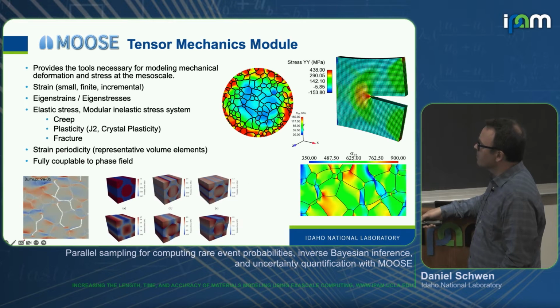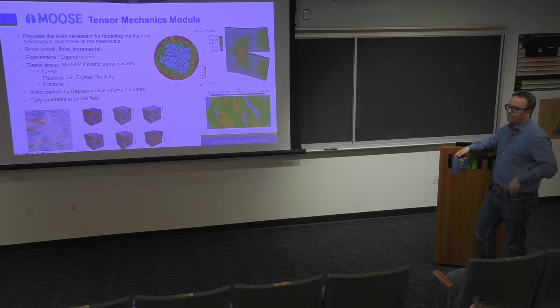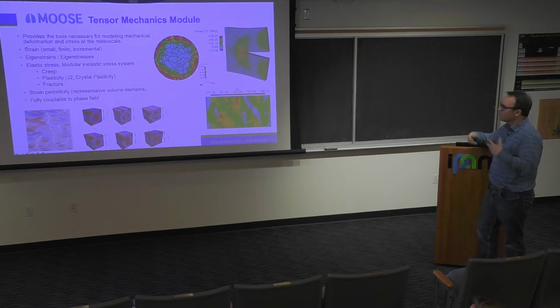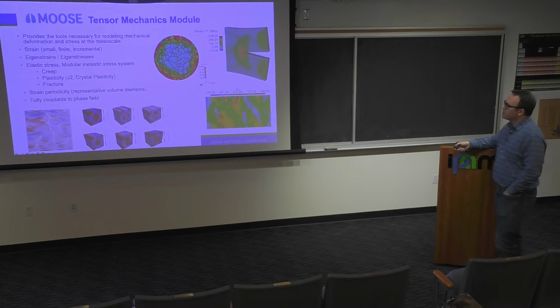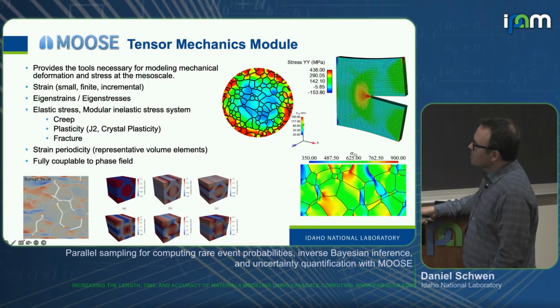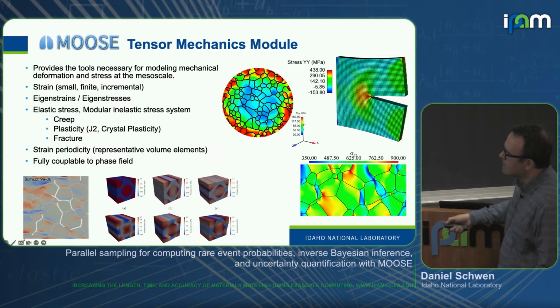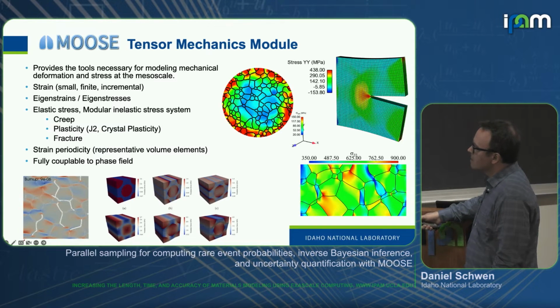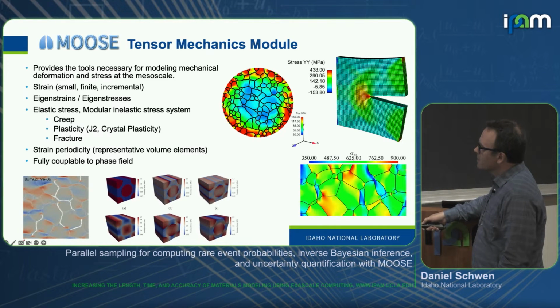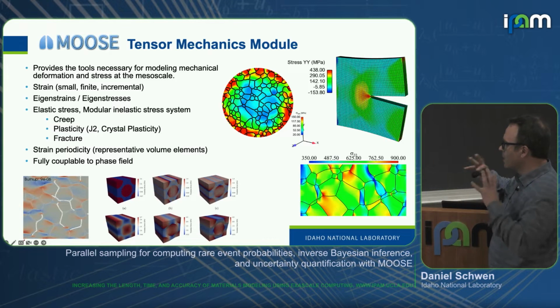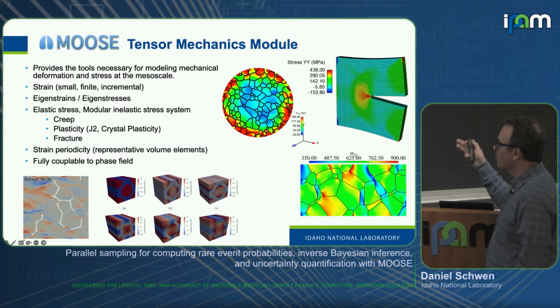So let me talk a little bit about mesoscale material modeling. The framework comes with a bunch of physics modules so that you don't have to implement all the basic PDEs. There's a lot of stuff already there, like the diffusion equation and, for example, stress divergence and everything that goes around it in the so-called tensor mechanics module. So we can deal with small and finite and incremental and total strain formulations, support eigenstrains, eigenstresses, creep, plasticity, like J2, crystal plasticity, and whatever other plasticity formulations, and fracture using XFEM or phase field fracture. And this whole thing is fully couplable in one big equation system to, for example, a phase field simulation or heat conduction.